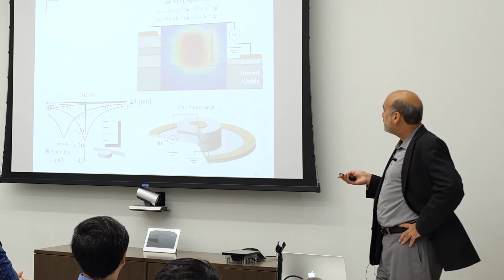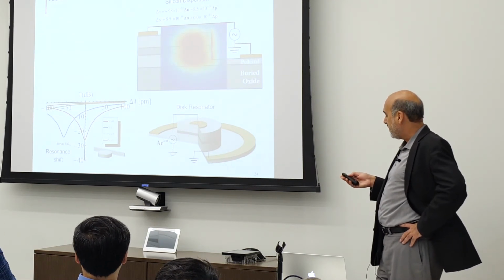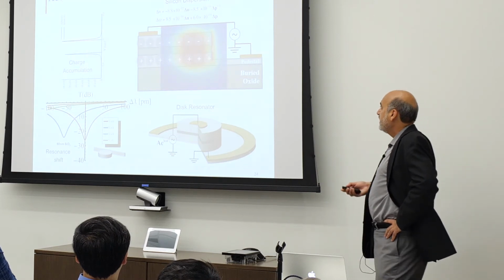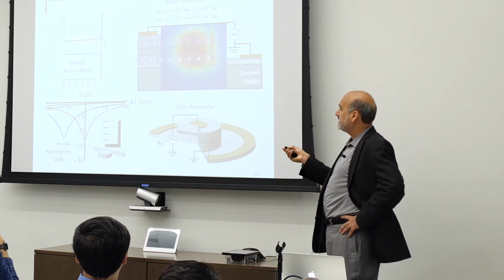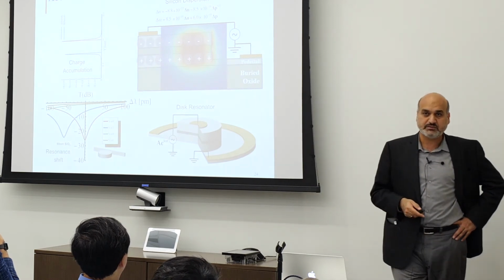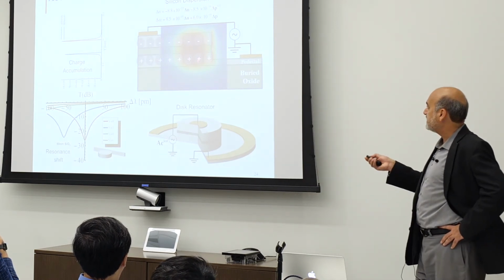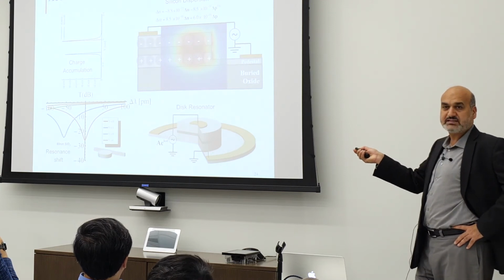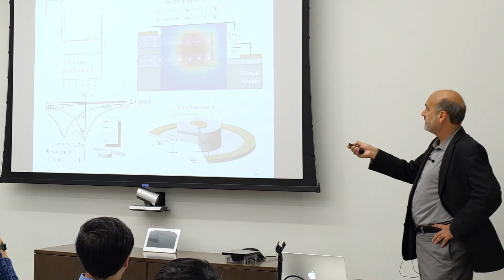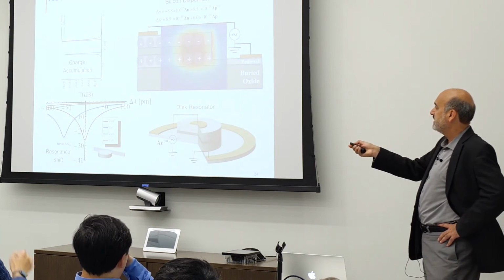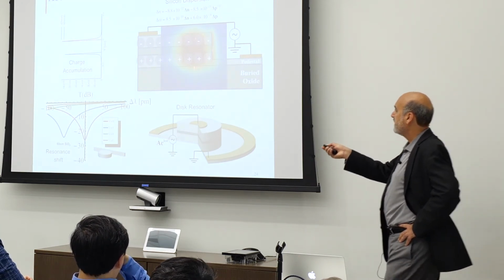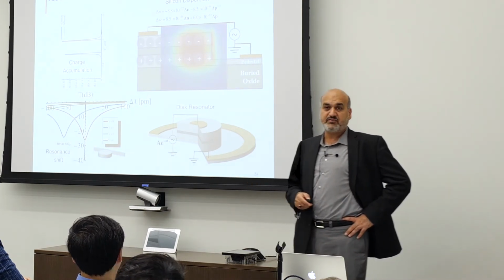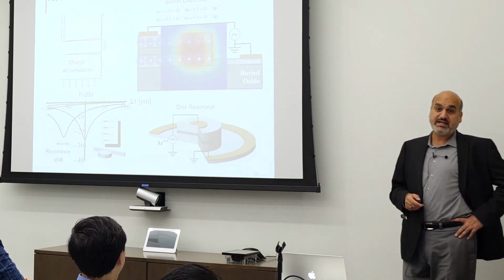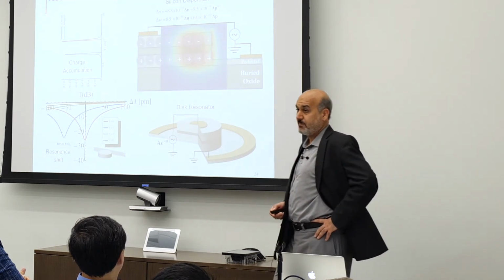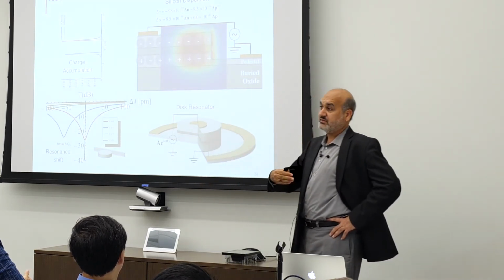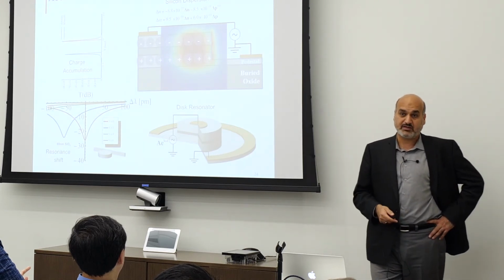So the way this device works is different from conventional silicon. In conventional silicon, you have one layer, and you have to inject or deplete carriers by a p-n junction. This is nothing but a capacitor. Silicon and oxide is a capacitor. So we apply the voltage between the two silicon layers, and then we have charges in them, and this results in a shift in the index of refraction without requiring a current. That's what a p-n junction has to do. Reducing the current will considerably reduce the power consumption.